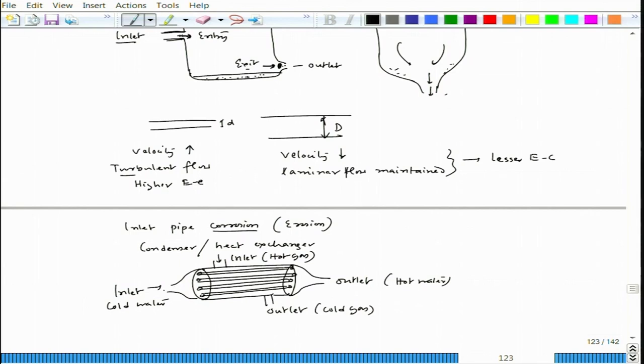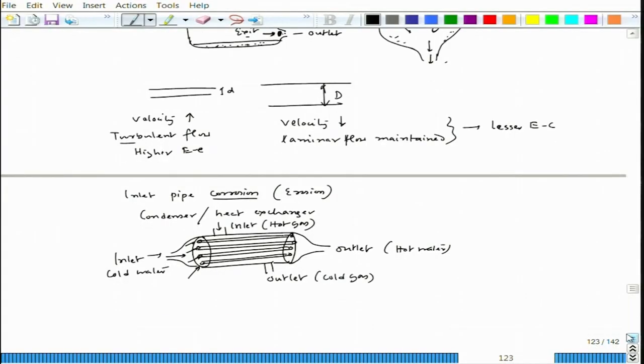So now when the water goes in the inlet, from the larger diameter it is going through a small diameter pipe. That means in the pipe entry part we will have a greater degree of erosion effect, because there will be a lot of turbulence. That turbulence would lead to a huge degree of erosion corrosion in that inlet section, okay. That is what is called inlet pipe corrosion, okay. So in order to stop that, people use a ferrule, okay. It is basically a pipe insert. So the pipe insert looks like this, fine. So now this insert is actually taken into the heat exchanger pipe.